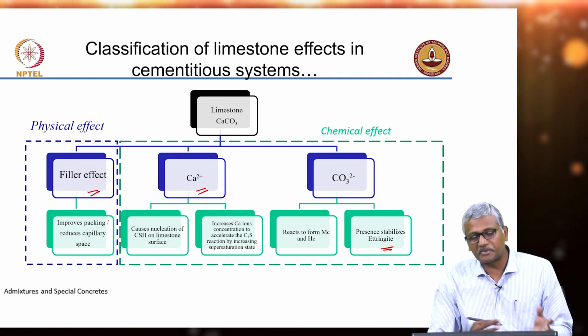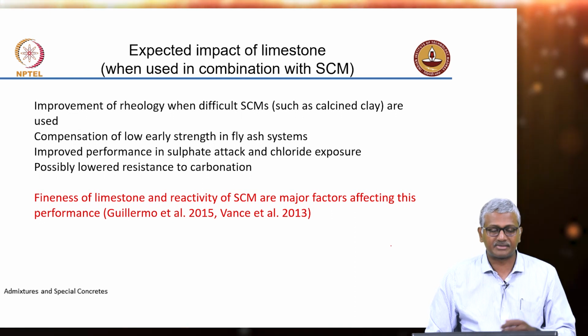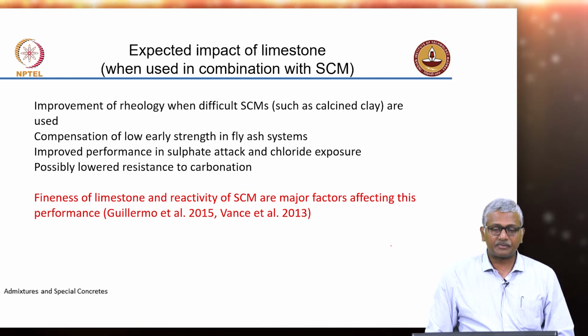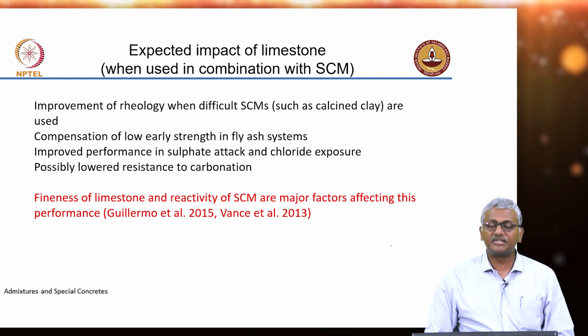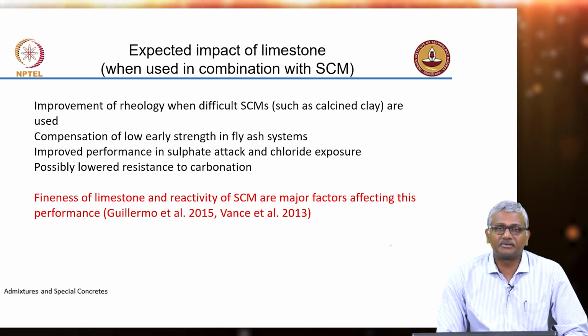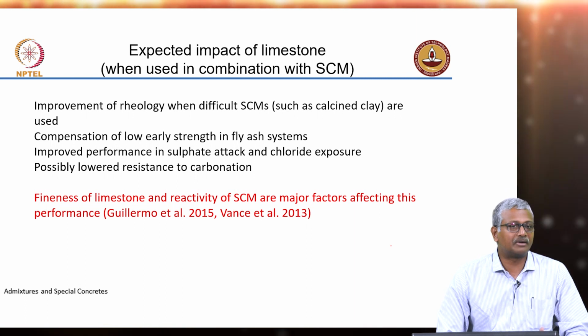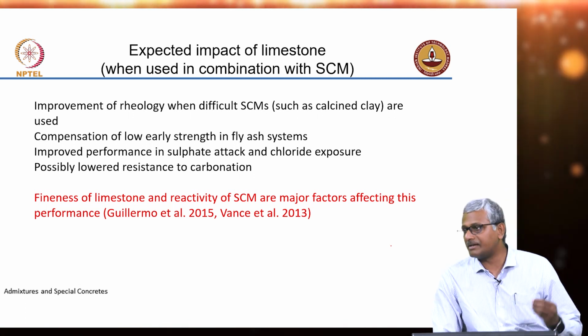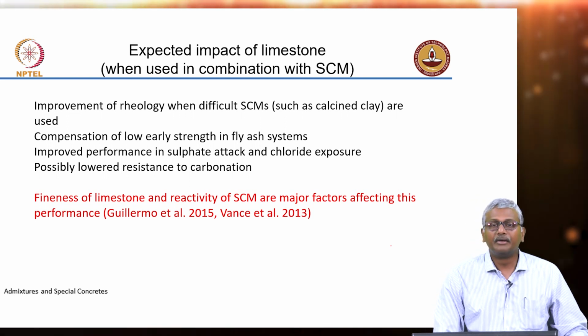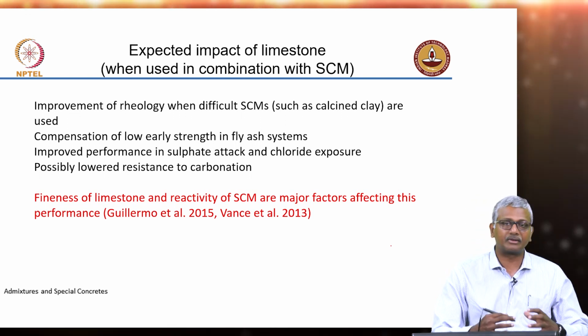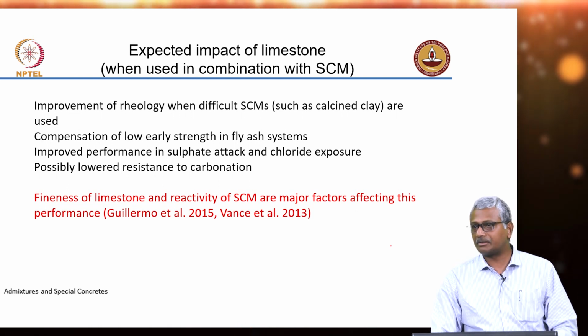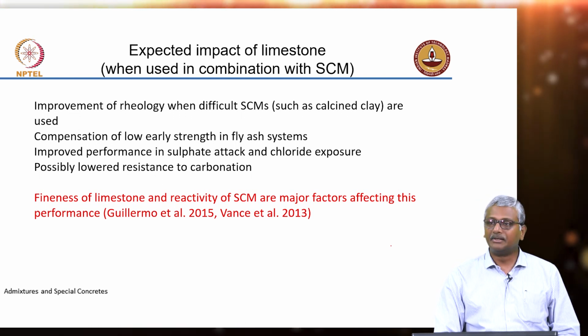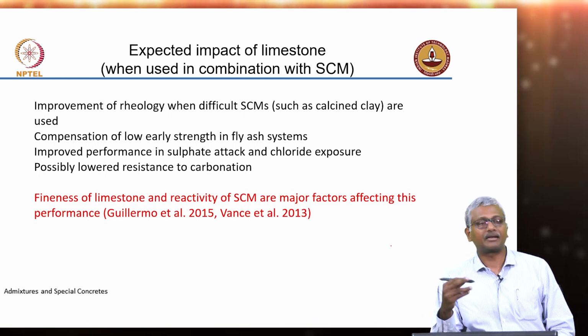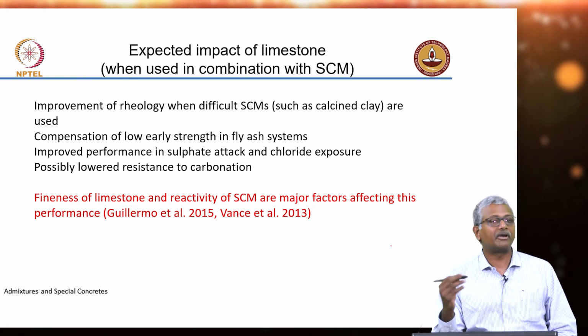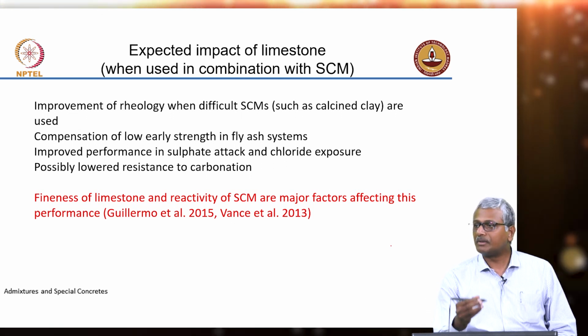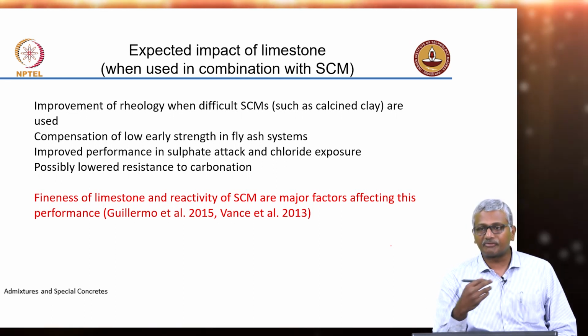Okay, anyway, that's getting too specific. We don't have to go to that extent to understand the system. So what happens when limestone is used in combination with supplementary materials? In general, when calcined clays are used, we know that intercalation of PCEs and other superplasticizers can take place in the sheets of the calcined clay. But in the presence of limestone, you are able to actually offset that effect to some extent. It gives better flowability to your system. In fact, for your plastering, to improve the applicability of plaster, limestone is an excellent material to replace Portland cement, because it gives that softness to apply that plaster.